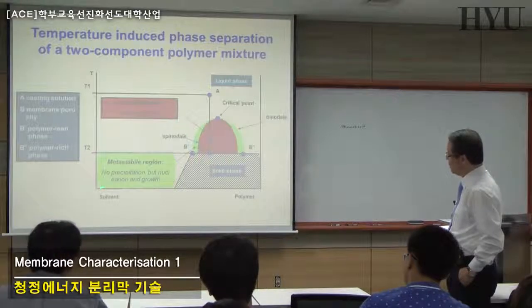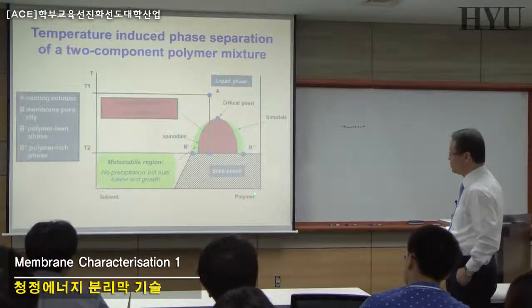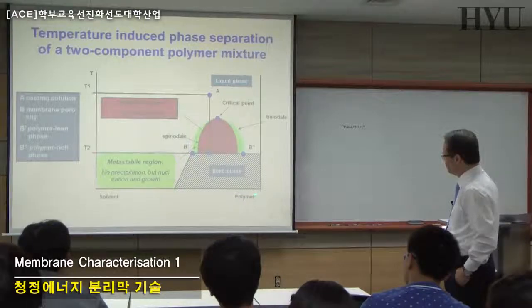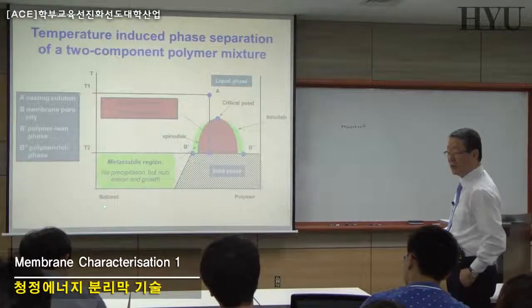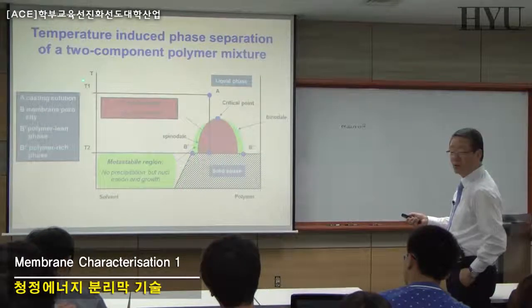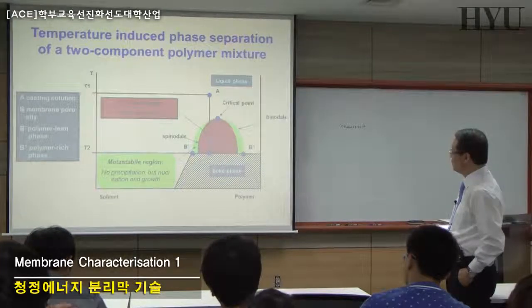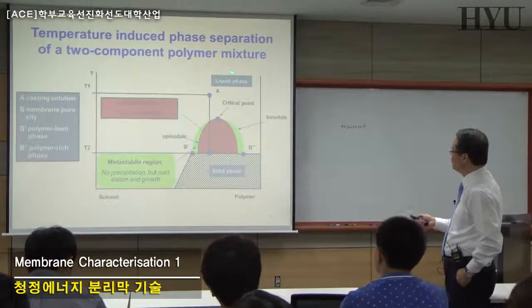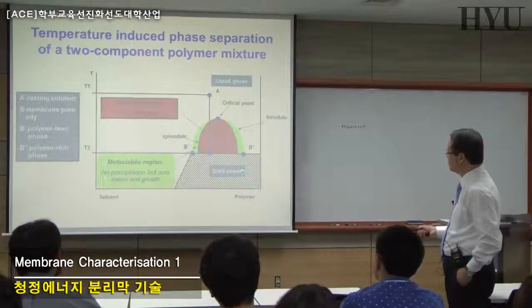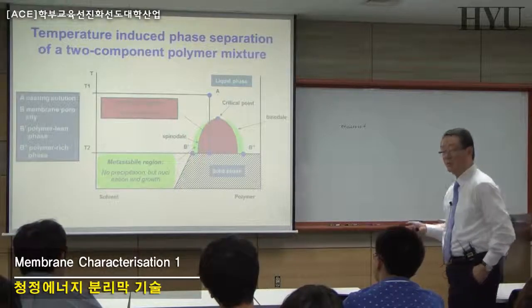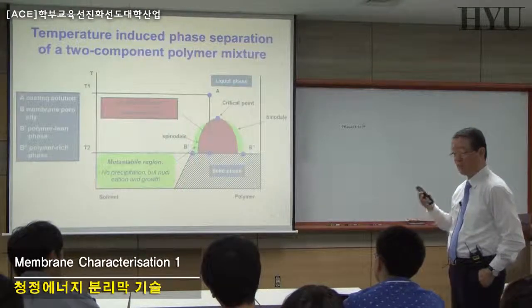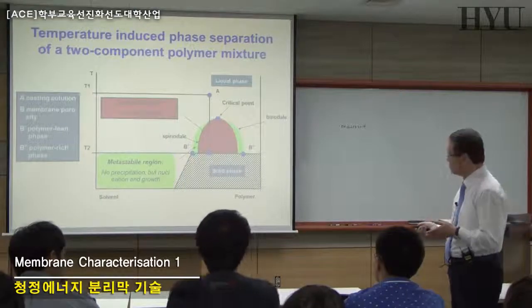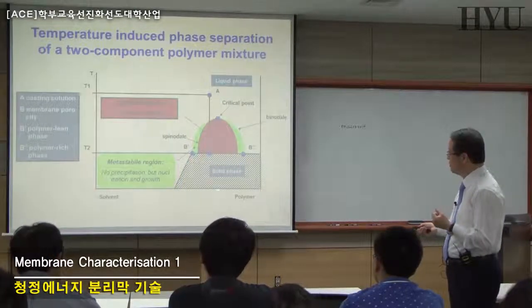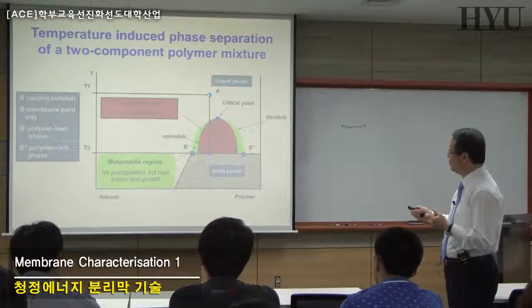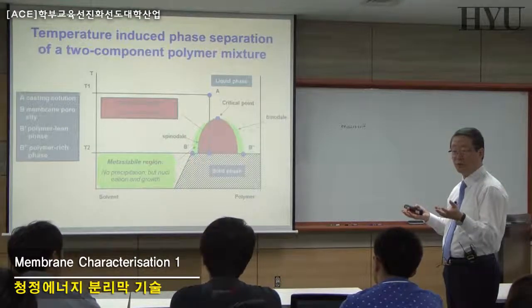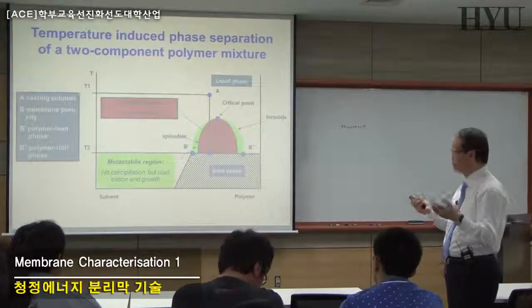When you have a solvent and a polymer, polymer concentration increases from left to right, whereas solvent concentration increases from right to left. And the y-axis is the temperature. When the temperature increases, you can have a liquid phase in some cases, and the solid phase. I told you that when you have your solvent and polymer, particularly this solvent is a latent solvent. So when you mix these two and increase the temperature close to your melting temperature, your polymer will melt and should be in the liquid phase.